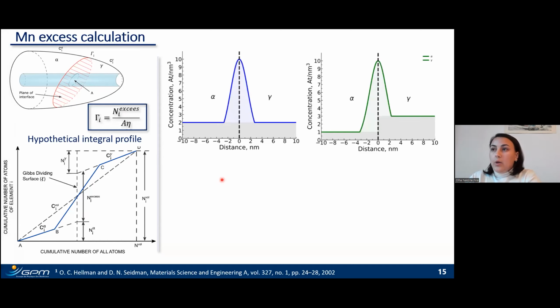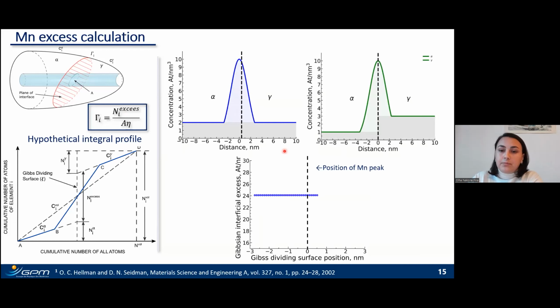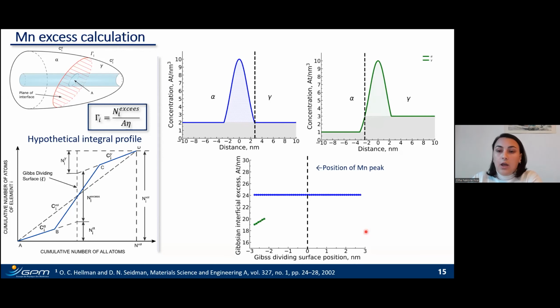When we have a symmetrical profile, so when the atomic fractions of solute atoms in both phases are identical, it is not a problem because, as you can see from the following animation, it doesn't matter where we place this Gibbs dividing surface, the value of manganese excess doesn't change. But it is not the case when the compositions are not equal on both sides, which is exactly the case of the present work. So from the next animation, you can see that the position of the dividing surface influences the excess value. So the question here is how to choose this position.